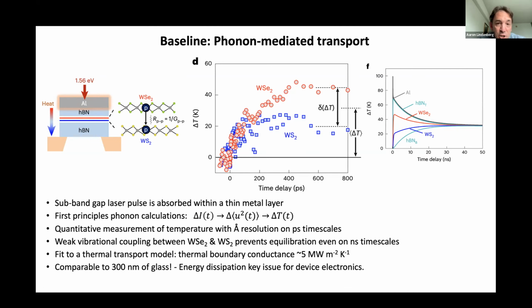And now what we're probing is the baseline phonon-mediated transport. This is like heat conduction, directly trying to probe the effective thermal resistance across these different structures. Of course, there are many interfaces in these samples. So you're really probing transfer of energy from the aluminum into the hBN, from the hBN into the 2D heterostructure, and so on.